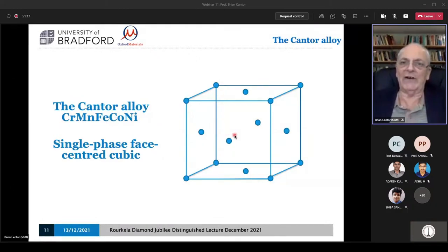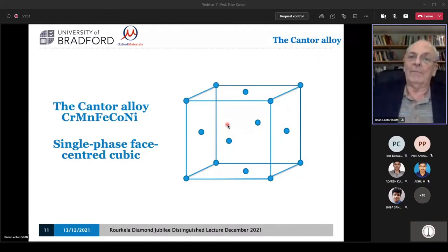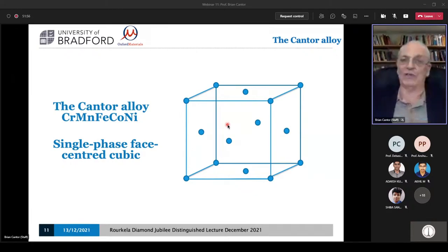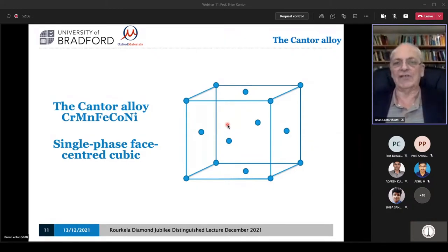But if you add binary and ternary systems, which we looked at, you find they don't mix so much. And we've seen that already. Copper, which is face-centered cubic, once you've added more than 1% of tin, it starts to form a compound. It forms a copper stannide, Cu6Sn5 compound. If you add carbon to iron, we've seen it, you get cementite, Fe3C, an iron carbide. You can't add elements into a starting crystal structure because you start to form compounds. Those provide the hardness for the materials we were familiar with, but if you add too much, it makes it almost impossible to make the material because they're too hard. They become brittle, they lose their formability, they lose their softness, you can't use them. That's why people thought it was a daft idea, a bonkers idea, to try and mix up so many components.